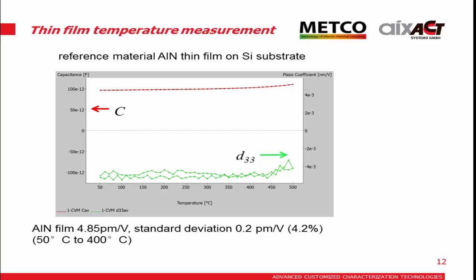So for a reference, on one hand we took quartz, which I'll show later, and we take aluminum nitride films because this is a stable material. It does not show ferroelectric behavior, but a piezoelectric behavior, which is rather low, around 5 picometers per volt.